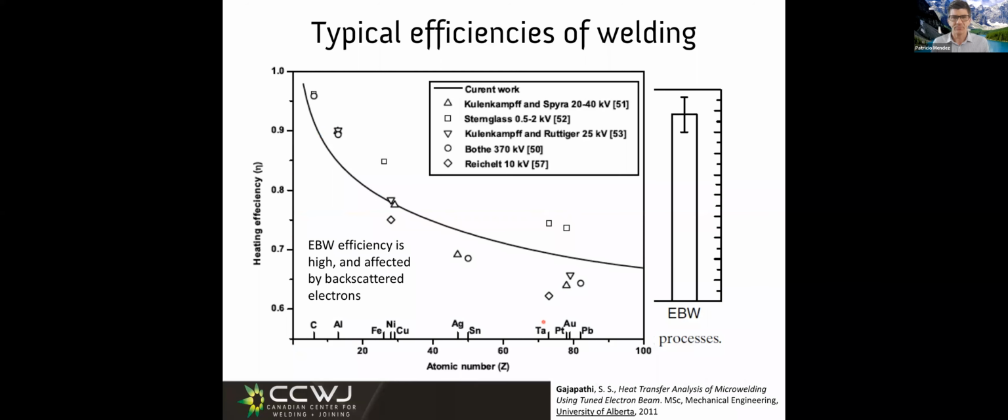Electron beam. Interestingly enough, this graph we're showing you about efficiency was calculated in our lab. We had a project on electron beam welding, and we needed to know the efficiency. And we learned something really cool. You know what we learned? We know from electron microscopy that we can make images from backscattered electrons. If we have no backscattered electrons, no images.